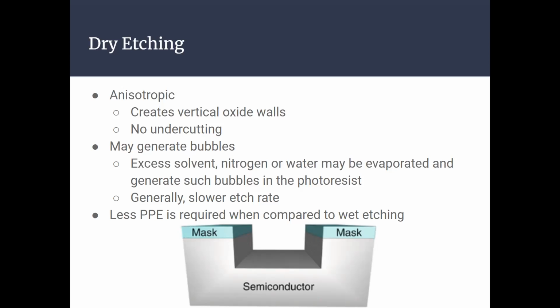And as I mentioned before, there's generally a slower etch rate just due to how the process works. And one benefit of the process itself is that less PPE is required when working with it compared to wet etching. Because with wet etching, since you're working with hydrofluoric acid, despite it being extremely diluted, hydrofluoric acid is very, very, very dangerous. As it doesn't burn you, it works its way into your bloodstream, reacts with the calcium in your bones, and then if enough calcium has reacted with the fluorine and the hydrofluoric acid, it will give you a heart attack when it blocks up your arteries.